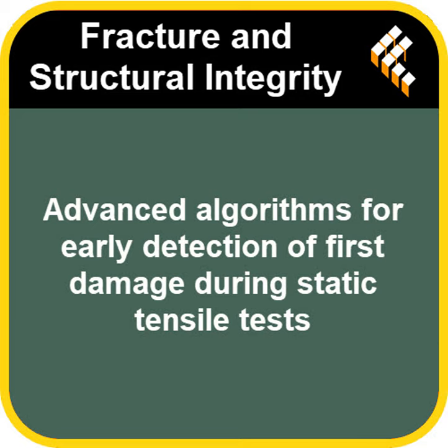And it keeps shifting that dividing line between the two chunks, moving it along the data. Yes, exactly. In each iteration, it shifts that dividing point forward by one data point. It's like scanning along the curve. For every possible split, it does a linear regression to the data points it thinks are phase 1 and another straight line for phase 2. Then it calculates where those two lines would intersect. And that intersection point gives an estimate for the limit stress for that specific iteration. It builds a two-line or bilinear model for every possible split point.